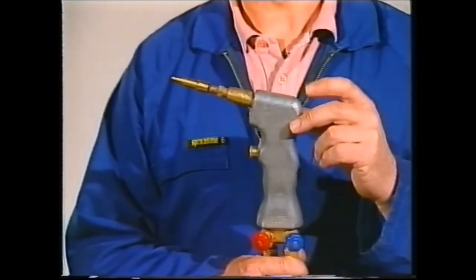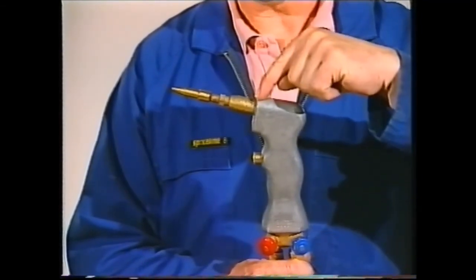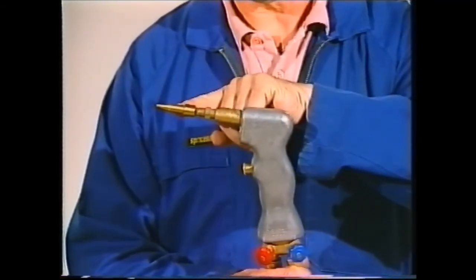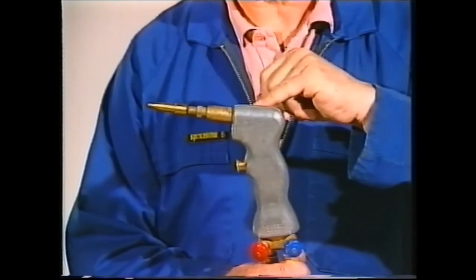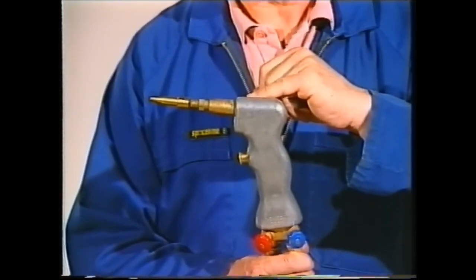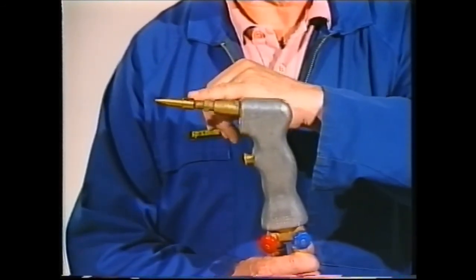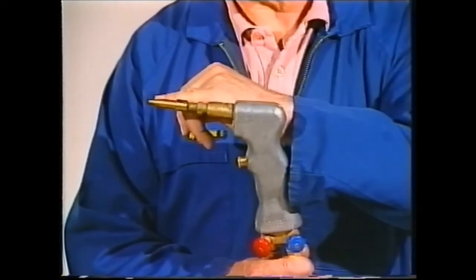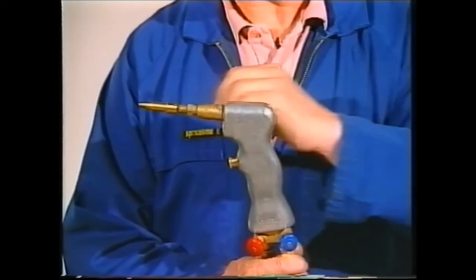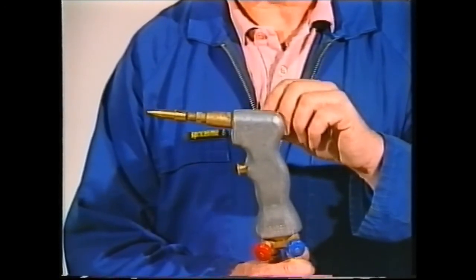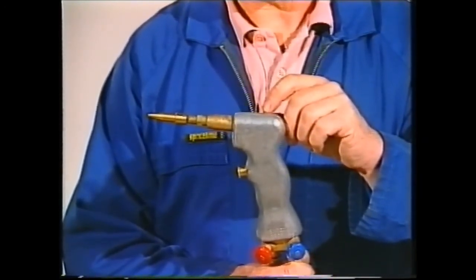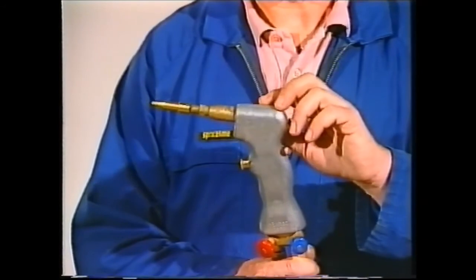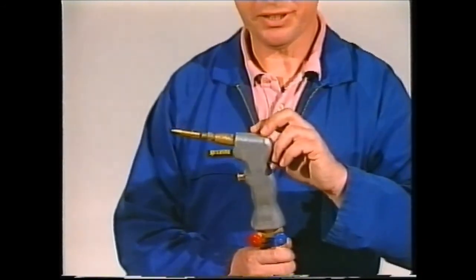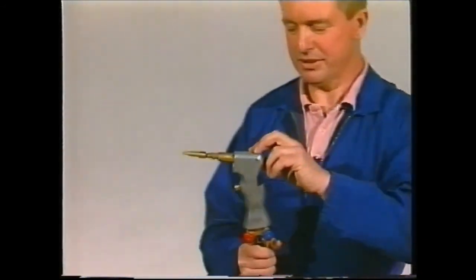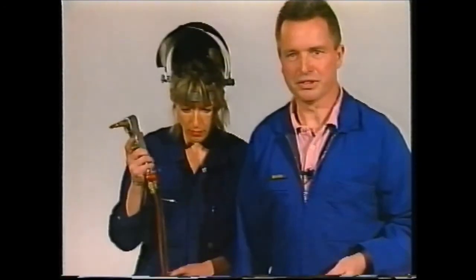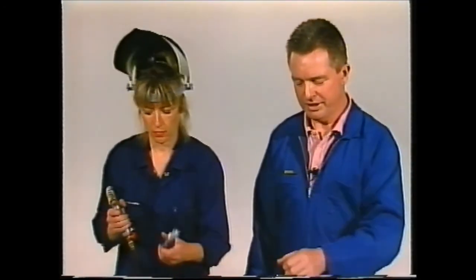Now, the torch also has a unique mixing chamber and special low velocity tips. It delivers the oxygen and acetylene in equal quantities, and the special low velocity tips deliver a very narrow concentrated heat pattern. And most importantly, it delivers a non-oxidizing flame. Now, I'm going to get Lynn over shortly, and we're going to start our demonstration by showing you some panel steel, the torch's lack of distortion abilities.